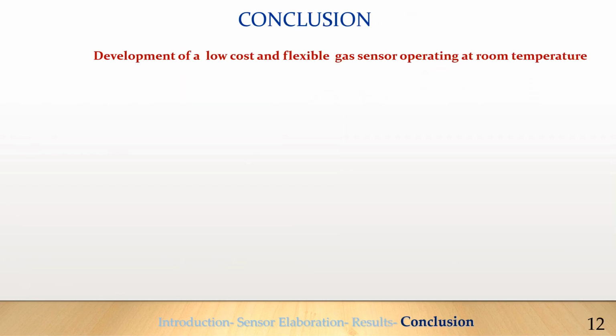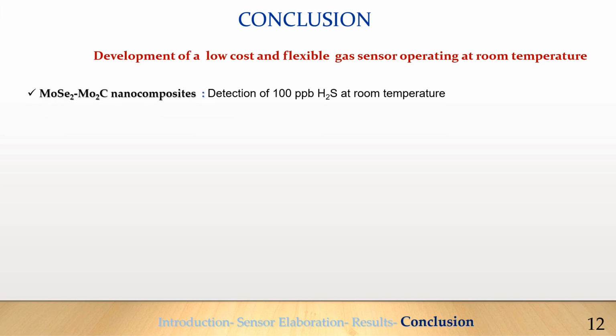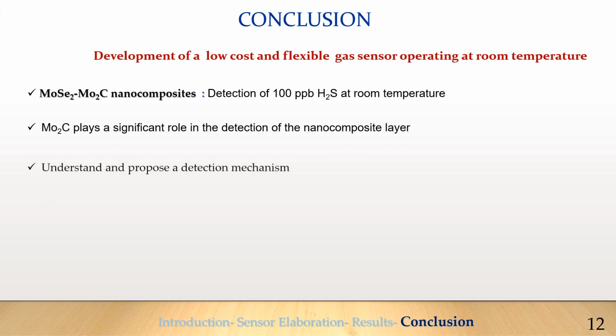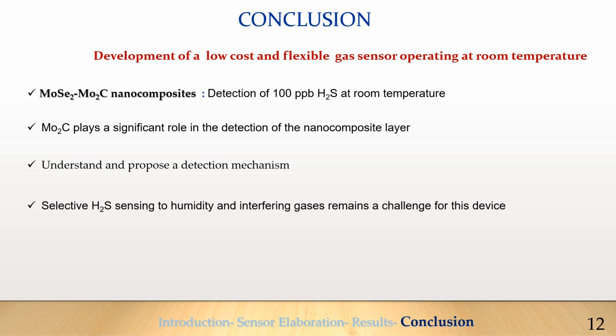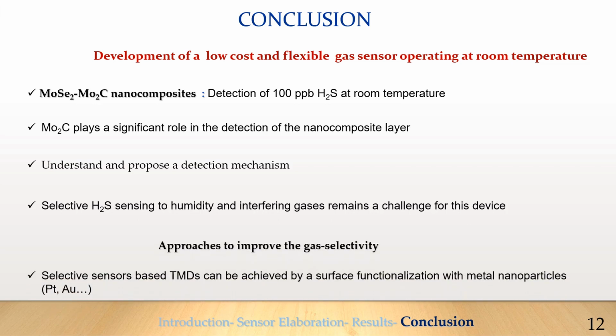In conclusion, we have successfully developed a low-cost and flexible gas sensor operating at room temperature. The novelty of this study is the use of the MoSe2-Mo2C material as a sensitive layer for a resistive gas sensor to detect 100 ppb of hydrogen sulfide at room temperature. Mo2C plays a significant role in the enhancement of the detection of the nanocomposite layer. We understand and propose a detection mechanism. The selectivity of sensing to humidity and interfering gases remains a challenge for these devices. We can improve its selectivity by surface functionalization with metal nanoparticles like platinum or gold.